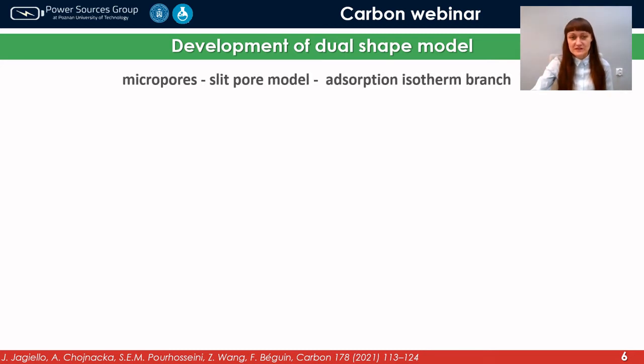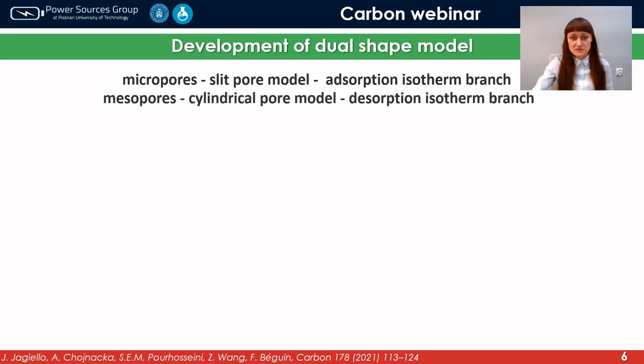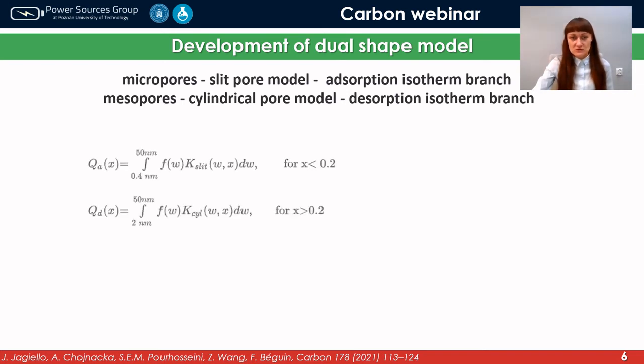Based on the presented data, we thought that maybe our approach is not so accurate. That's why we started to develop a new model, in which we postulated that the micropores should be analyzed by the slit pore model using the adsorption isotherm branch, while mesopores should be analyzed by the cylindrical pore model using the desorption isotherm branch. So to calculate the pore size distribution, we were using the dual kernel method, in which we fit simultaneously parts of the adsorption branch, which are lower than 0.2 relative pressure, and parts of the desorption branch, which are higher than 0.2 relative pressure, using the slit kernel and cylindrical kernel respectively.